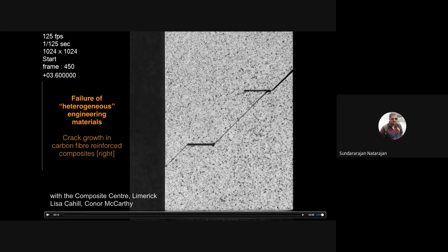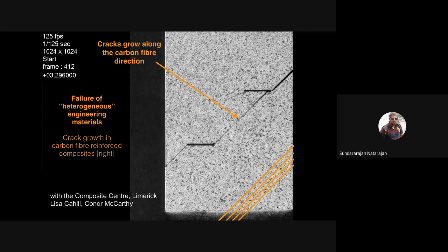And our objective was to see if we can use XFEM to simulate this observation. So those are the cracks which are growing along the fiber. The fiber is along that direction. And since the fiber is stiffer than the matrix, you can see that the crack has grown along a particular direction,